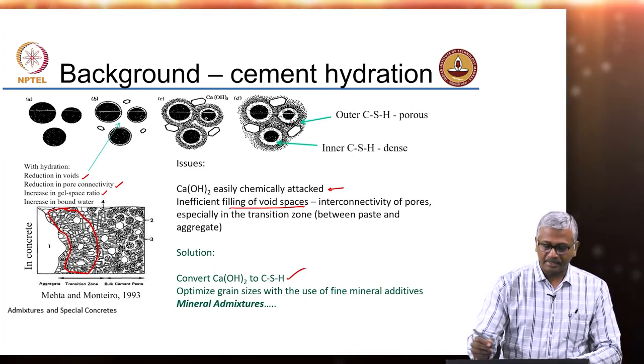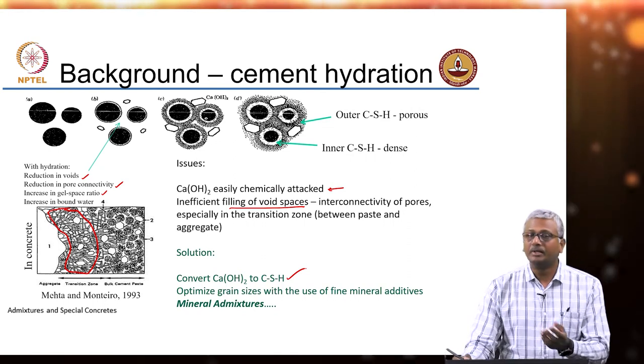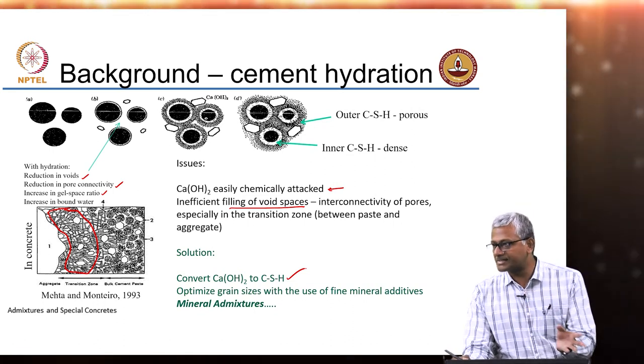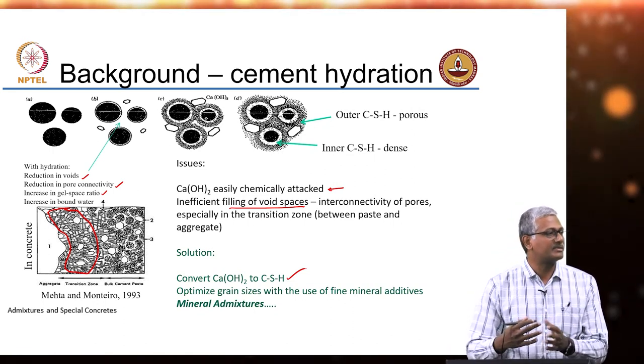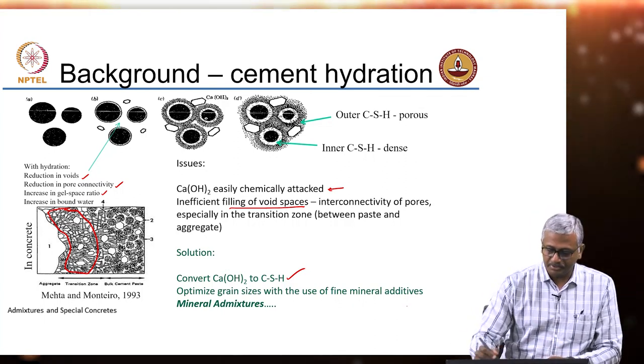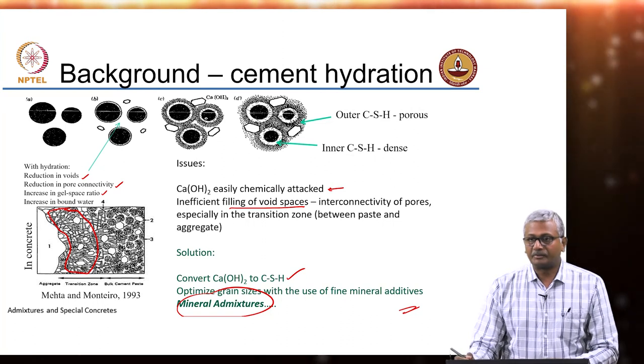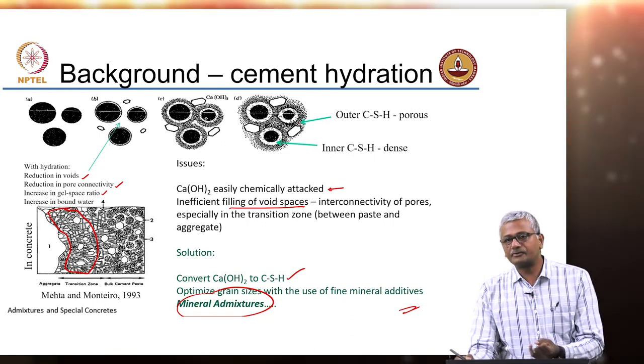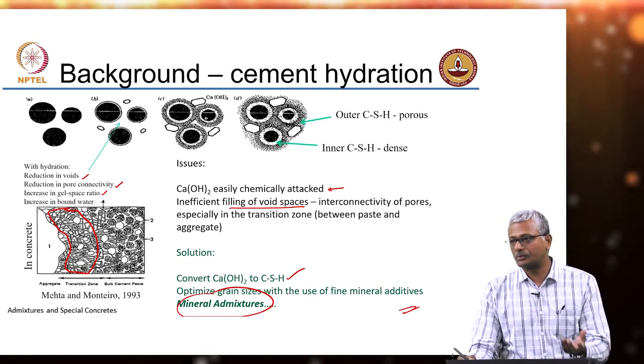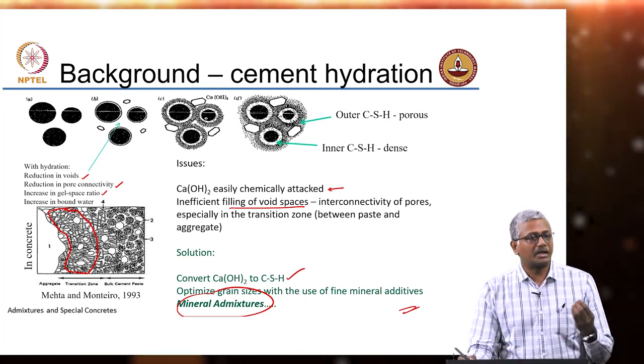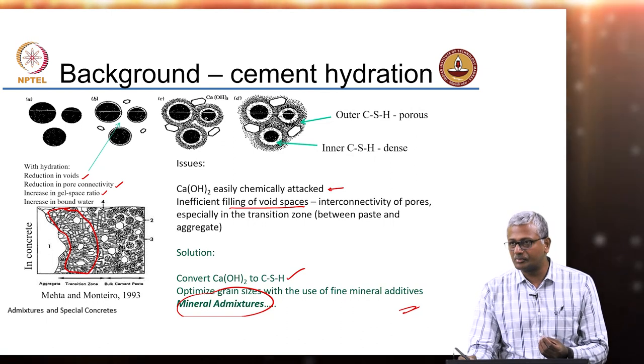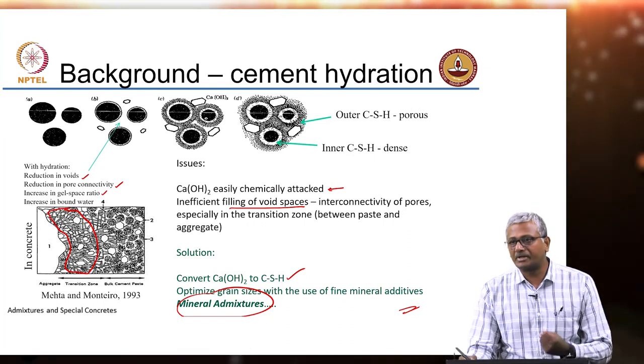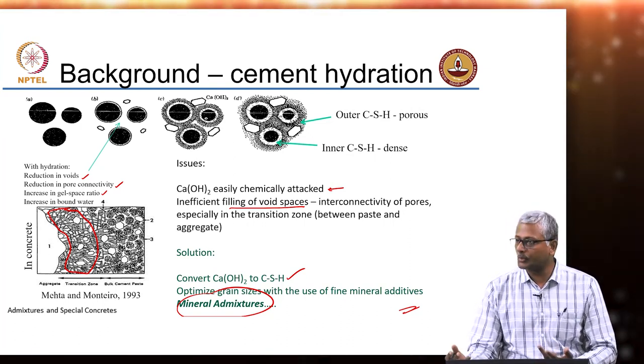Conversion of calcium hydroxide to CSH, combined with optimization of grain size by using mineral additives of varying fineness — some coarser, some finer than cement — produces much more efficient packing of the entire system. This is where mineral additives become important. Two primary aspects: first, mineral additives should have reactive silica that can convert calcium hydroxide to CSH; second, they should have an optimized grain size distribution that fits into the gaps provided by the cement concrete, optimizing packing of the system.